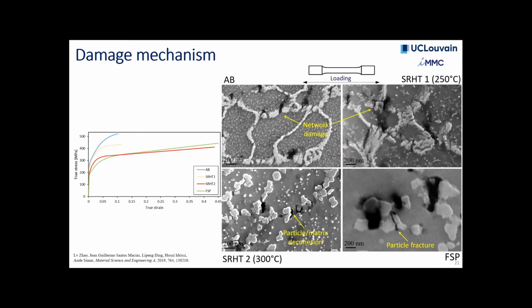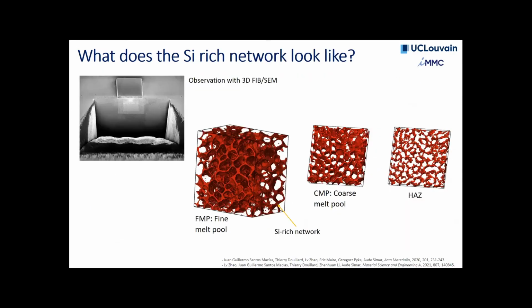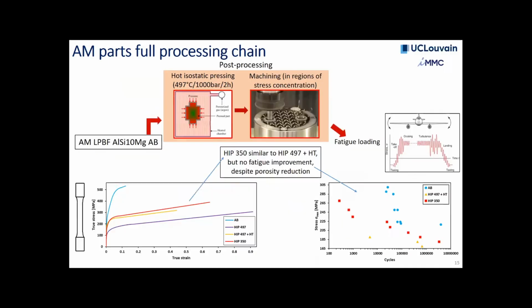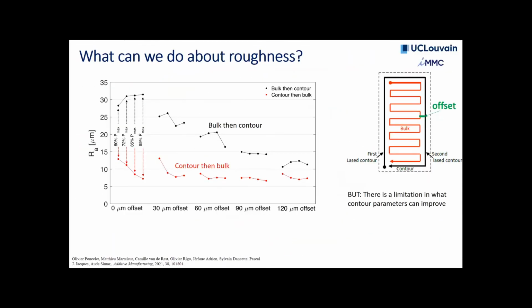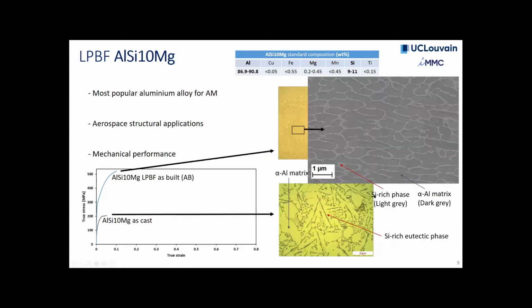And this is true in cast alloys as well. It has been shown in the literature, and that's what inspired us at the time, that in cast alloys where you have these really huge silicon networks, if you break these down, it also improves the ductility. So this is a known aspect of friction stir processing. Okay, so you want to keep the silicon particles small, but the network you want to have big, and this is not something that you can achieve with DED because you also have particles which are larger, right?